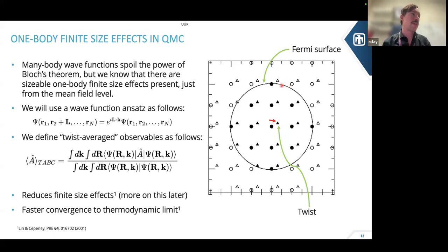So for things like molecular crystals and strong insulators, the window of K space that you need to describe the system is just not nearly as big. You might have your Fermi surface, but you're going to have to pop way up somewhere here to be able to go to the next excited state. So oftentimes in those situations, you can get away with even a gamma point calculation, which, for non-solid state practitioners, is the K point corresponding to 0, 0, 0.